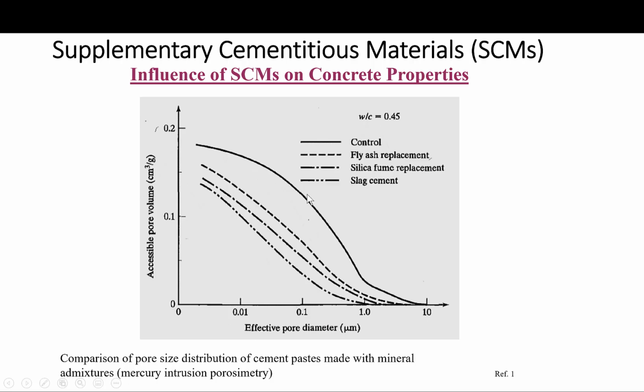This is the control mix, and this is the fly ash replacement, which is lower. This is for silica fume, lowered even more, and with slag it's lowered even further. The effect of slag here may be due to the higher replacement, but nonetheless, this gives an indication of how the use of these mineral admixtures or SCMs will refine the pore structure by reducing the overall porosity and the pore size.